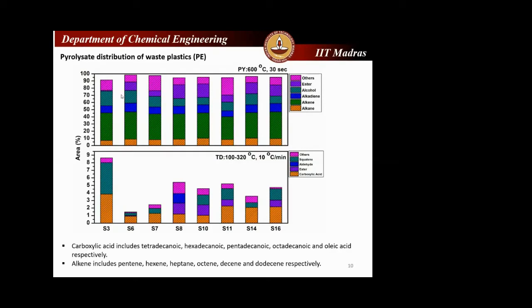What did I get in the thermal digestion regime? I got most of this. If you can see here, the carboxylic acid area percentage is higher, because over a period some compounds had been adsorbed to the sample, and some samples have oil content. So this belongs to the carboxylic acids, which include tetradecanoic acid, hexadecanoic acid, pentadecanoic acid, and octadecanoic acid.